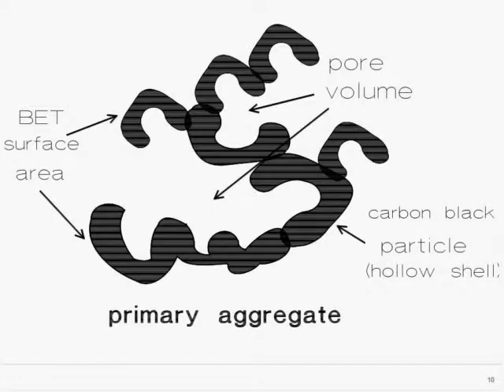Try to explain the morphology of the Ketjenblack. This is essentially an amorphous product. It is not a crystalline product, with both large surface area and large pore volume. Surface area, we measure this by nitrogen, and also as indicated, the pore volume is also reported on the certificate of analysis.